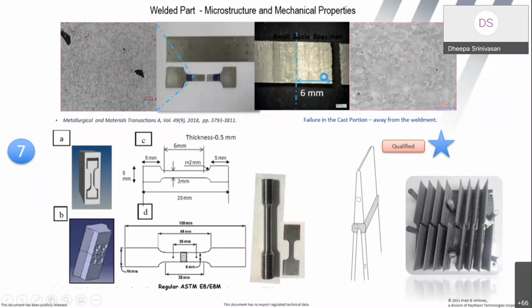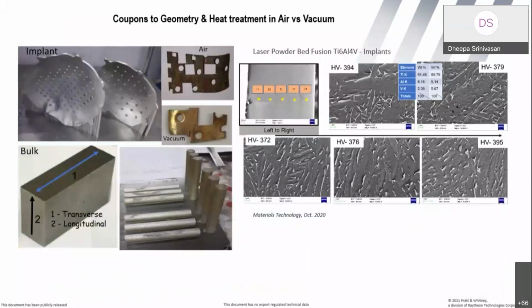Both the tie line, you can see the blue dotted line, the tie line representing this particular interface between the additive and the cast, across this particular line, both the additive part as well as the weld joint are intact. The failure or the weak zone happens only in the investment cast part. So this is another very important challenge you need to watch out for. And then I move to the next challenge.